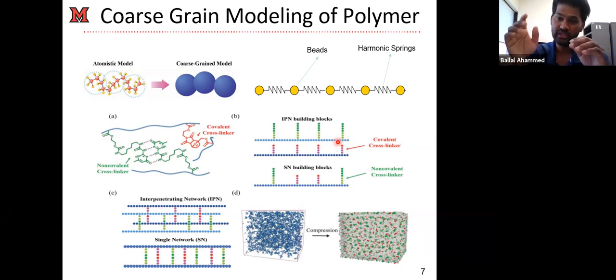So we define the different particle types. When you start the simulation, we said that if these two types of particle, which are responsible for the covalent crosslinking, come within a certain distance, then LAMMPS will decide that there will be a FENE bond between them. As I remember, we did it with some kind of fix, so maybe you can just search the FENE bond in LAMMPS. Probably there is a fix associated with it. I have used that, but it's been almost 2.5 years, so my knowledge may be a little bit rusty. I guess we define a different particle type, and in the simulations, when these two particle types come within a certain distance, we define the new bond, which maybe is done by a fix, I guess. Yeah.